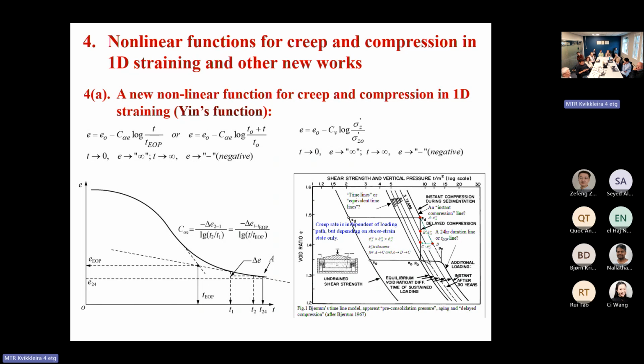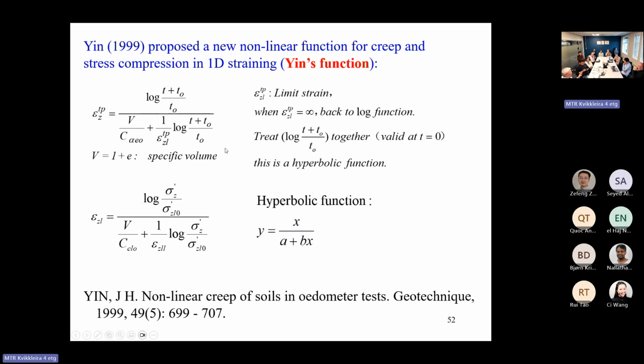How to solve this problem? I propose a new function which is very simple and can fit data very well. It's a combination of a hyperbolic function and a log function. So simple. I spent a few years to figure out a good function. You can see the hyperbolic function has a limit. The log function has no limit, but the log function can fit the data for a certain range very well. So I combine the log function with the hyperbolic function. It's a beautiful function to fit this nonlinear behavior. Based on this new function, I can also derive a new elastic visco-plastic model.